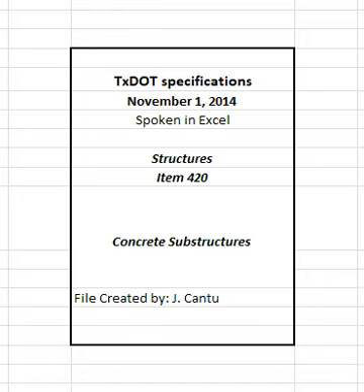Do not use the vibrator to move the concrete to other locations in the forms. Do not drag the vibrator through the concrete. Thoroughly consolidate concrete along construction joints by operating the vibrator along and close to but not against the joint surface. Continue the vibration until the concrete surrounding reinforcements and fixtures is completely consolidated. Hand spade or rod the concrete if necessary to ensure flushing of mortar to the surface of all forms.